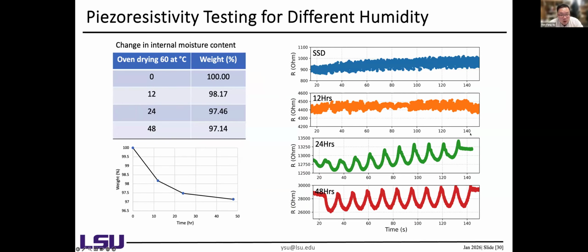And we want to move one step further to discuss the environmental effect. As previously Dr. Eun said, environment is really important to our infrastructure. So we first start from the different humidity levels. Once we cast the sample, we submerge the sample all the way in water for 2 days, to make sure it's in the saturated surface dry condition, SSD condition. Then we measure and put it into the oven to create the different humidity conditions.